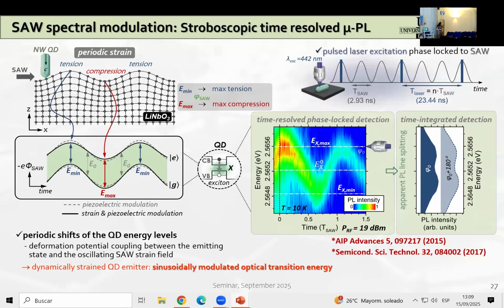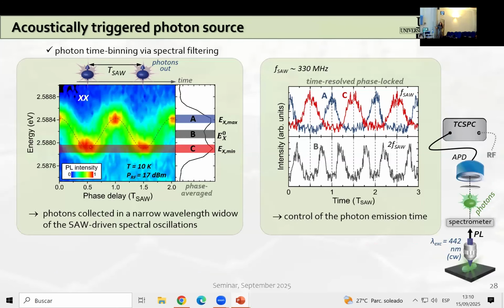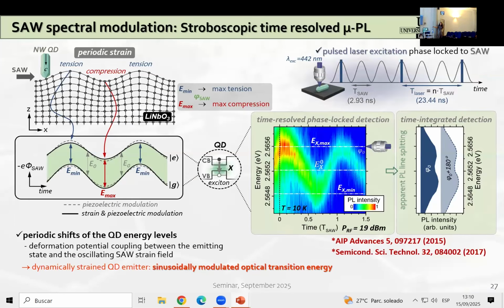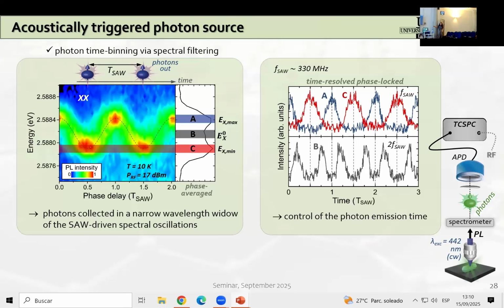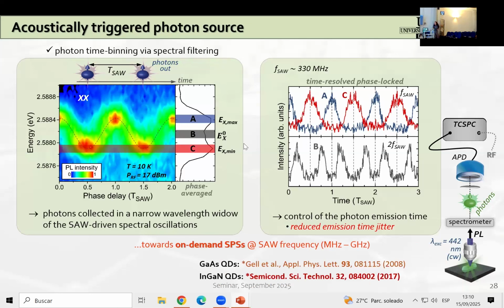But then in the next slide, here or here, you see that the intensity is larger for particular strain states then. Oh yeah, this is different. These red dots here. Yeah, this is different. Because what we have done here, you see, this is time decay. So this is a time resolved detection, right? But what we did here is we used pulse excitation, but this was time integrated detection. So in this case, you can actually track, and this is only in the case of the bi-exciton because it has actually, I think I have some transparencies. Let's try to find one that can explain it better.